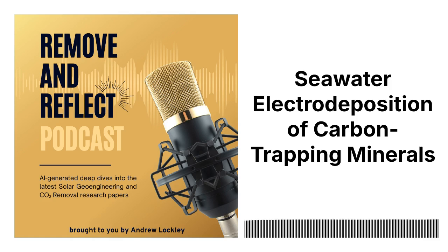They start experimenting with pumping CO2 right into the seawater during electrolysis. And what they found was pretty amazing. This CO2 injection dramatically increases the formation of calcium carbonate, which, as we know, is a fantastic way to trap carbon dioxide. It's a natural way to lock it away. Exactly. And while this opens up all these possibilities for both material production and carbon capture, the researchers were also very upfront about the potential challenges. This mineral formation could increase the electrical resistance in the system, which could make it less efficient. Makes sense. So that's definitely something they're looking at.